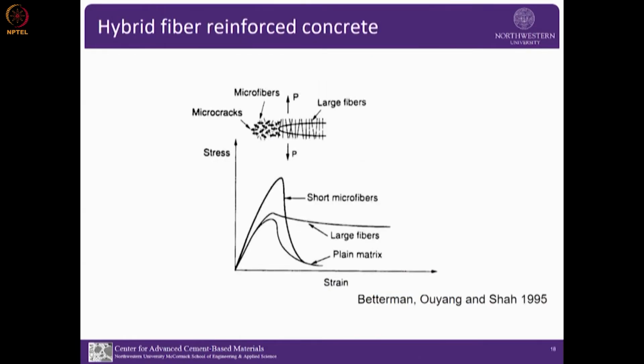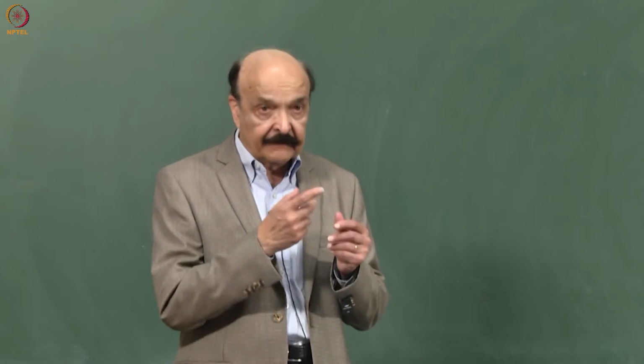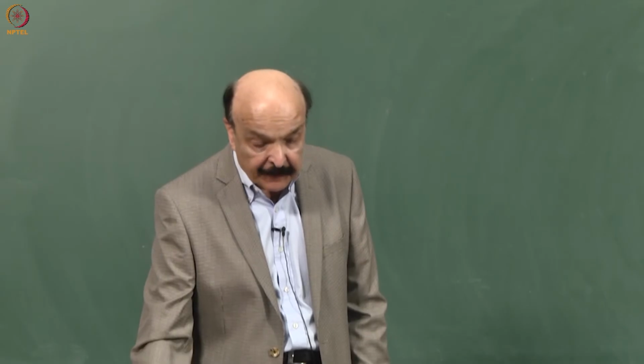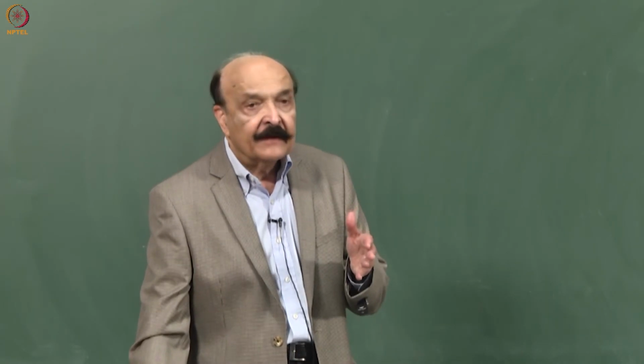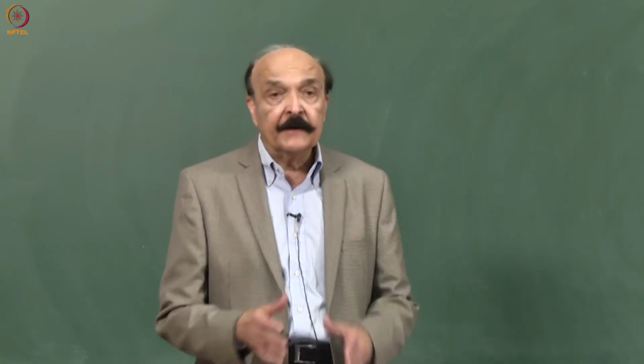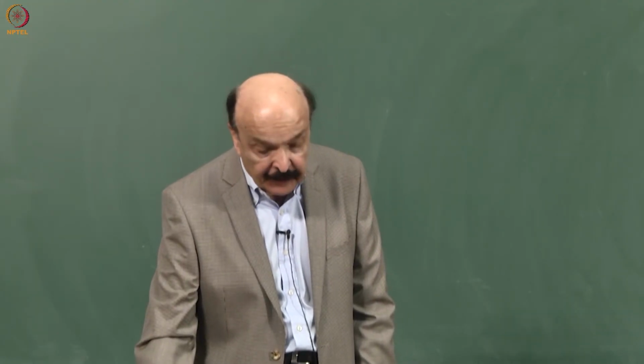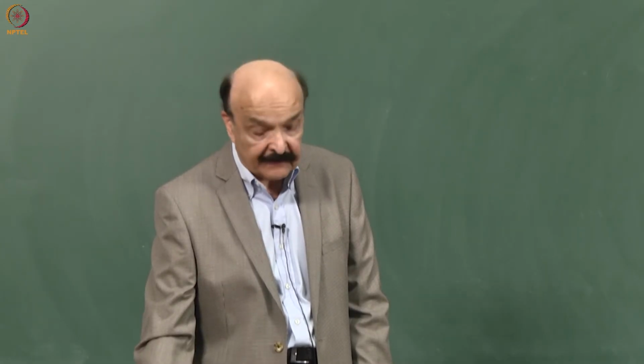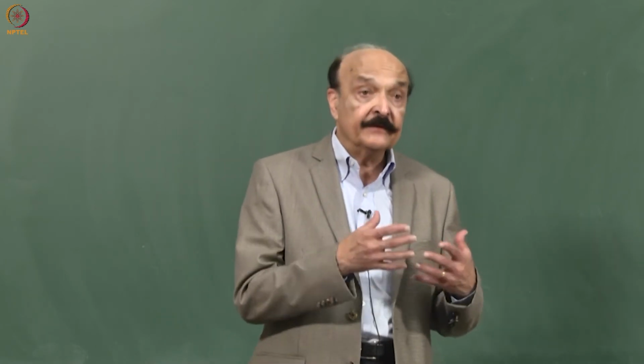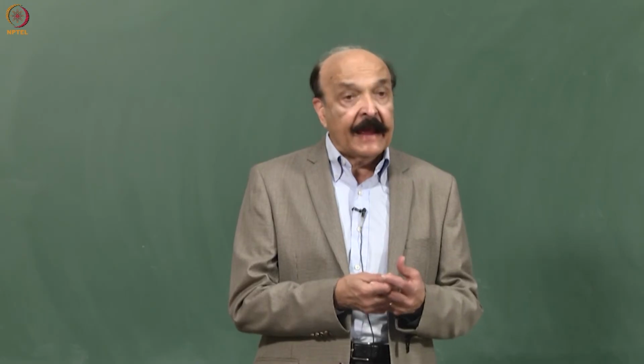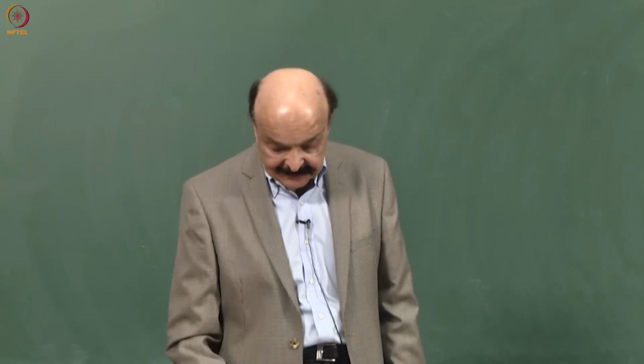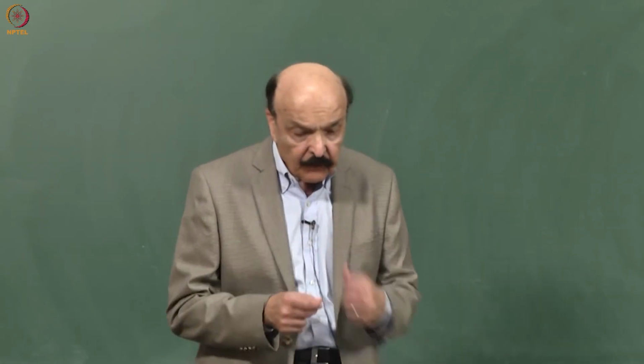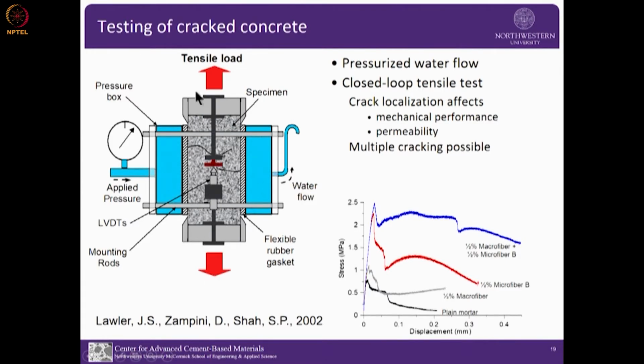Okay, another thing which people have studied quite a bit is so-called hybrid composite. In the hybrid composite, we know that short fiber can, like earlier as I showed, increase the fracture strength, but they are short. So once the crack develops, they do not have as much long range crack controlling property. Large fibers can do it, but they do not really increase the tensile strength. So you can combine the two and produce results which have a very, very fine crack width and also post-peak ductility. And to show you an example of this, we did a test. These were mortar specimens reinforced with fibers and subjected to tension. So there will be cracks.